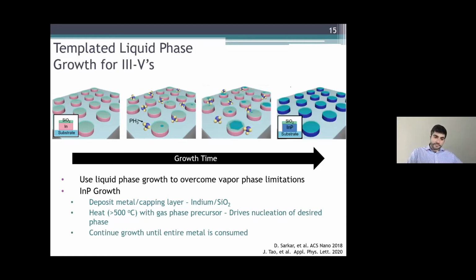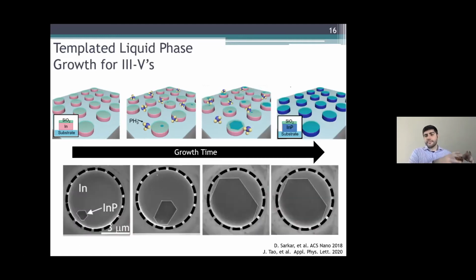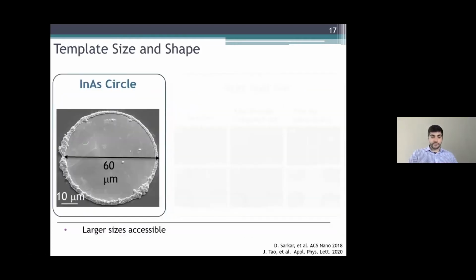And if you look at some SEM images of how these materials grow, what you can see on the bottom here is that we have this indium template, and what we're showing is, at different growth times, how an indium phosphide crystal might nucleate and then start growing to consume the entire template. We can also control the size and the shape.